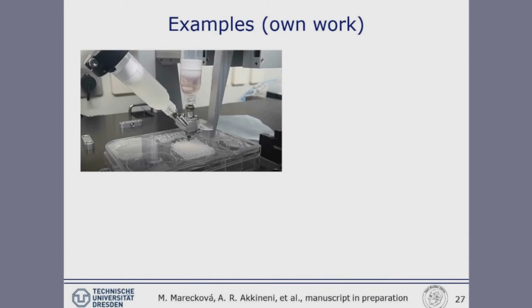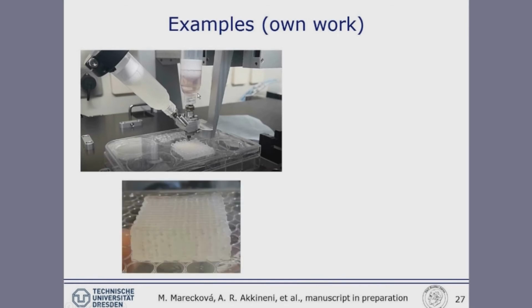We have done similar work, still unpublished. Can show you the setup. So this is the double extrusion nozzle, of course, connected to two different syringes for the two materials. We also printed successfully macroscopic scaffolds, maybe even looking a little bit more defined than those printed by the colleagues from Nottingham, to kid them a little bit.